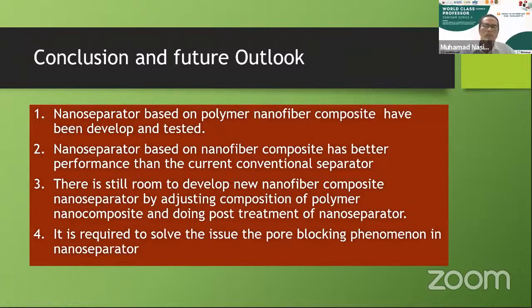First, nanoseparator based on the polymer nanofiber composite has been developed and tested. Second, nanoseparator based on nanofiber composite has better performance than the current conventional separator. So there is still room to develop new nanofiber composite nanoseparator by adjusting composition of polymer nanocomposite and doing post-treatment of nanoseparator. Fourth, it is required to solve the issue of the pore blocking phenomena in nanoseparator.